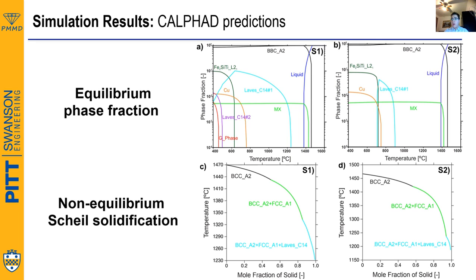Now, going forward with the CALPHAD predictions, CALPHAD allows us to compute the equilibrium phase fraction and the non-equilibrium solidification behavior for our two samples. These allow us to get an insight when designing these materials into what type of phases and microstructure we want, so we can tune, for example, homogenization and aging temperatures in order to get the goal of maximizing, in this case, L21 and minimizing the Laves phase. In the top two images, to be specific, we observe the phase fraction of both samples versus temperature.